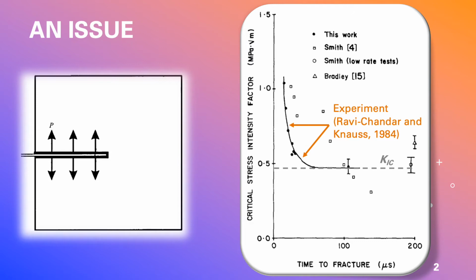Measured values of the stress intensity factor at the moment of crack initiation, when the time to fracture is small, for Homalite it's less than 50 microseconds, showed a strong difference from the critical stress intensity factor measured during the quasi-static tests. That of course contradicts the classical Griffith-Irwin approach. In view of the dynamic dependence of the stress intensity factor on the time to fracture, it would be very important to simulate the described experiment using the innovative approaches of solid mechanics developed to date.